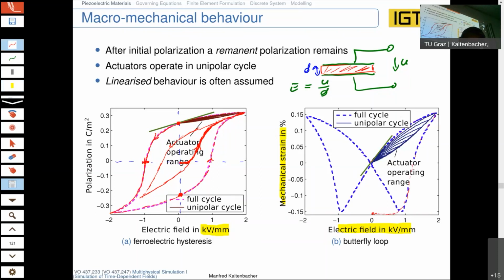And what we have here is something coming from a measurement, because these are real measurements, so we never know where the zero point is, and that would be the remnant strain, and that is clearly not zero as shown here. That was just due to the measurement.